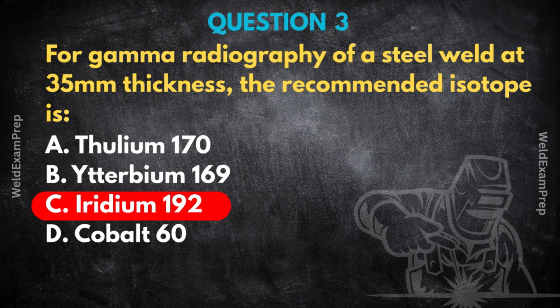For steel, in that sort of 10 millimeter to 70 millimeter range, especially around 35 millimeter, Iridium 192 is the workhorse. Its energy level is just right, good penetration, but also good sensitivity to actually see the defects in those medium thicknesses. Okay, so it's a balance. Strong enough to get through, but not so strong you lose the detail.